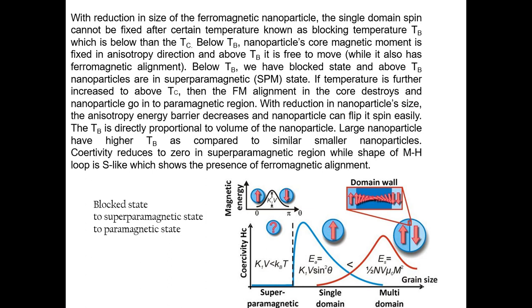This is also a significant challenge for data storage applications, because the blocking temperature is usually well below room temperature. For data storage, we need nanoparticles with a Tb above room temperature so that we can block their spin in a certain direction. The blocking temperature Tb depends on the volume of the particle and the anisotropy of the particle, so understanding Tb is essential.